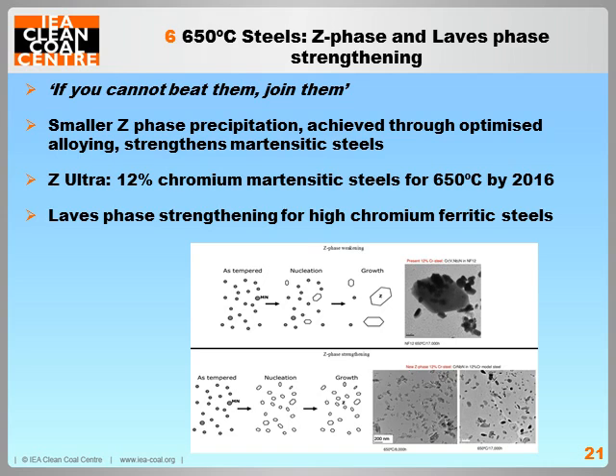Improving the long-term creep resistance of high chromium martensitic steels, such as 12% chromium martensitic steels, is a promising route for developing a 650 degrees Celsius steel, as they have inherently higher resistance to steam side oxidation due to the higher chromium levels. An interesting strengthening concept is to promote the formation of small Laves phase and Z phase precipitations during the fabrication of the parent material, thus turning the weakening mechanism found in existing martensitic steels into a strengthening mechanism.